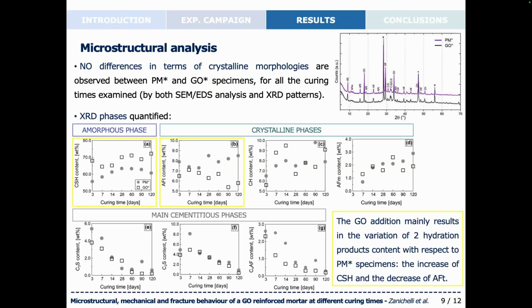As far as the microstructural analysis is concerned, no differences in terms of crystalline morphologies have been observed between the PM* and the GO* specimens for all the curing times considered. As you can see, there is an example of an XRD pattern on the top right part of the slide for both PM* and GO* specimens. Then in the lower part of the slide, the XRD phases quantified are plotted against the curing time. The more significant results have been obtained for the amorphous phase, that is the CSH, and for the ettringite, that is AFt.